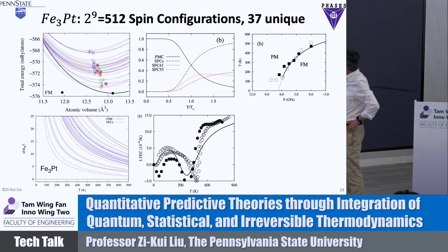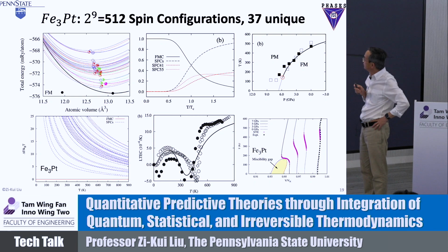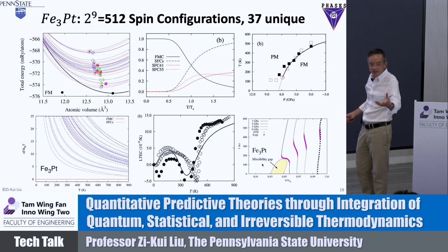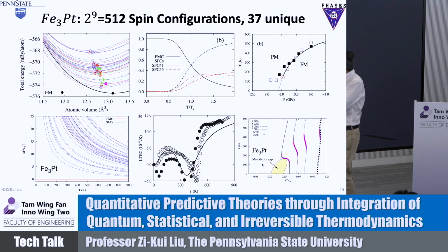Now, if we change this pressure to volume, what do we see? Each curve is for a fixed pressure. This dotted line is with 0 pressure, ambient pressure. You see the volume sort of increases first, and then the volume decides to not increase anymore, then decides to decrease, and then increases again. And then, of course, there is a lot of theory to explain this, talking about the bonding change and so forth, right? And it turned out there's no soft mode here.